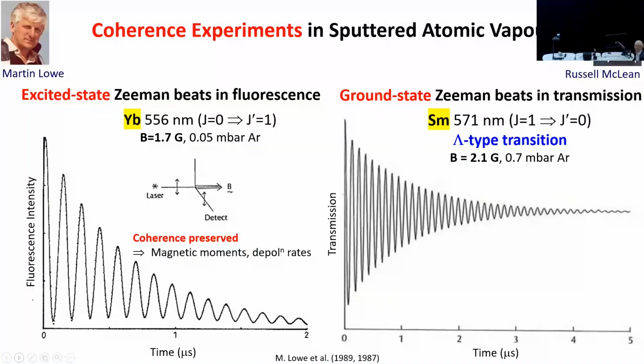But we're very interested to see whether we could do coherence experiments. And here, this shows ytterbium in a magnetic field of 1.7 Gauss. You have polarized laser light coming in, and with the magnetic field the direction of polarization rotates and you see a quantum beat, a beautiful quantum beat. This is a 0 to 1 transition, which means that theoretically you can get 100% visibility. This we use so the coherence is preserved apart from the rare gas, which is present, and that's what you're trying to measure. And you can get magnetic moments from the period of the beats.